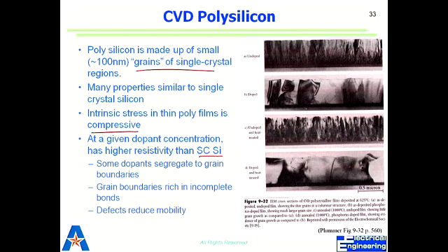Right? So simple logic tells us, instead of having a bulk of a complete single crystal which you can dope to make it conductive, now you have grain boundaries. Those grain boundaries would become part of the resistance or the conductance. So you have those extra boundaries, interfaces where charge carriers have to pass through. Would they be posing a hindrance to their flow, or would they be helping the flow? They'll be hindering the flow, right? In undoped form, they'll be hindering the flow. So that's why it has higher resistivity. At a given dopant concentration, it has higher resistivity than single crystalline, right? So we dope it while we are depositing it to make it metallic.